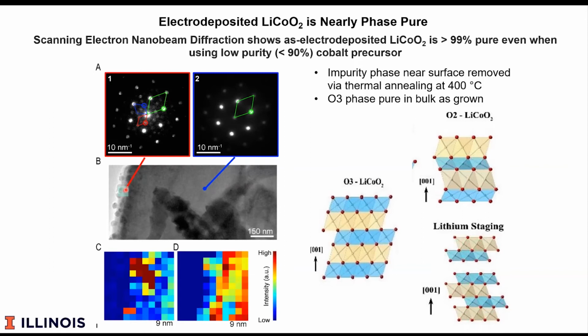We can see in experiment that once we remove the surface phase, both the kinetics and the cycle life improve dramatically. Very much an engineering aspect, but we find that we don't need to use pure cobalt precursor. Most of the impurities simply don't fit in the crystal lattice, and if you use impure precursors, a significant number of impurities will simply settle to the bottom of the deposition bath and can be removed at some future point. So somewhat fortuitous, but probably important for a practical application.